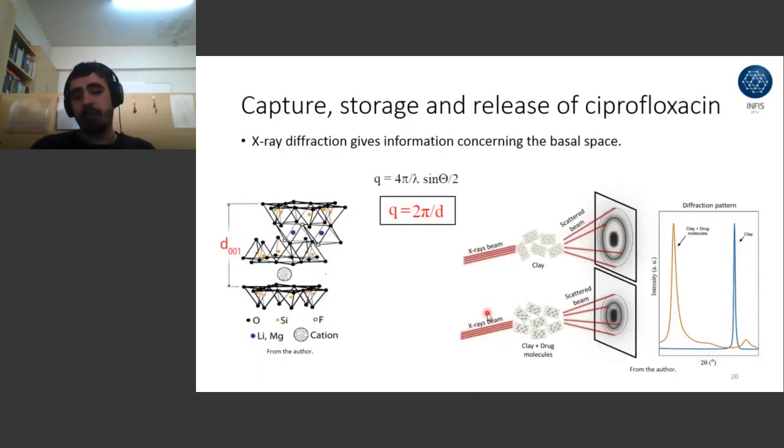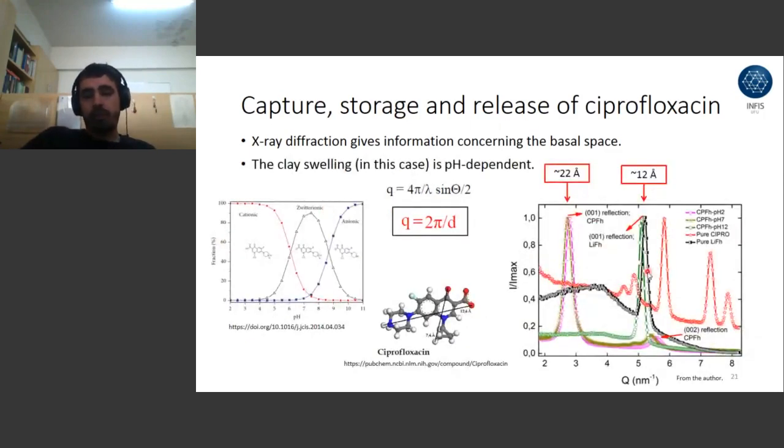With X-rays, for example X-ray diffraction, we can have a direct measurement of the basal spacing of the clay particles. Specifically, a family of Bragg reflections related to this spacing are the 00L reflections. The first peak that we see in a diffractogram of a clay mineral is usually the 001. If we look at the angular position of this peak, we can calculate, using Bragg's law, the interlayer space, as long as we know the thickness of the clay layers. So I did that, and I'm showing you here